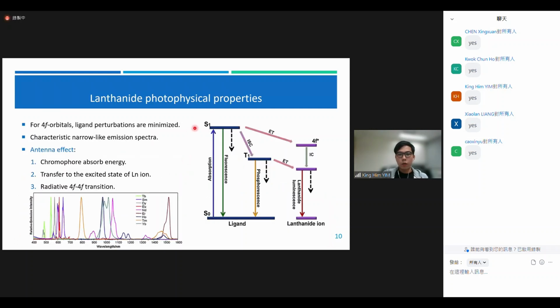Okay, and then I will introduce some of the lanthanide photophysical properties. Lanthanide exhibits very unique photophysical properties, because as I mentioned before, for the 4f orbital the ligand perturbation is minimized, since it is well shielded by the 5s and 5p orbitals. Therefore, lanthanide exhibits a characteristic line-like narrow emission spectrum. The right-hand side shows a simplified Jablonski diagram of the emission of lanthanide ions.